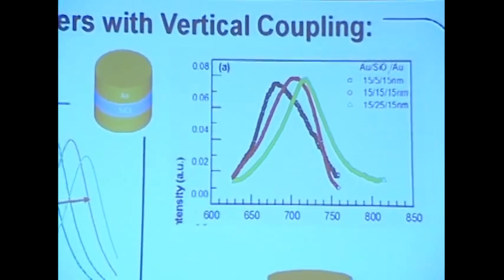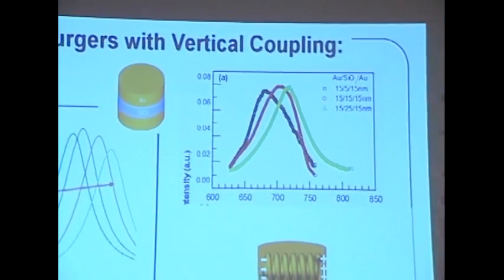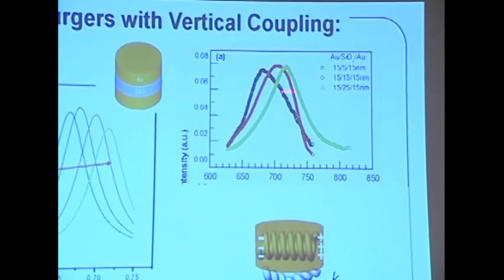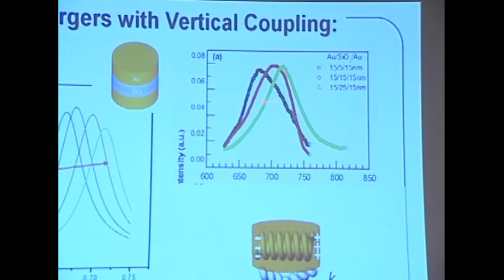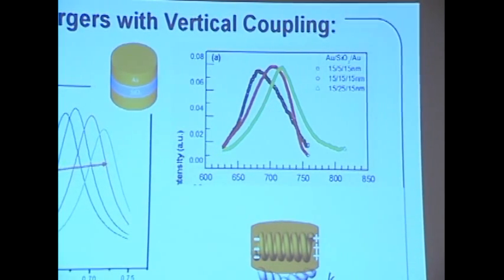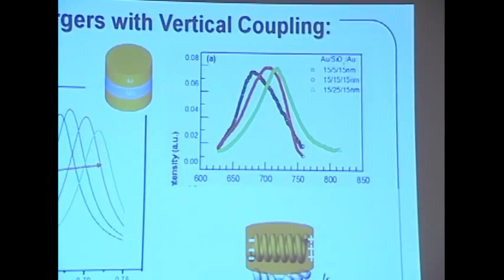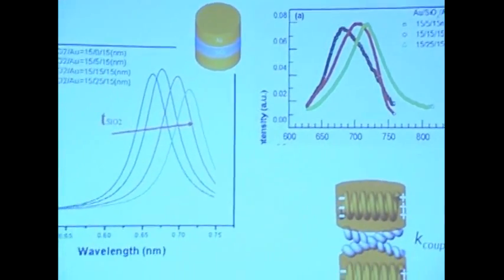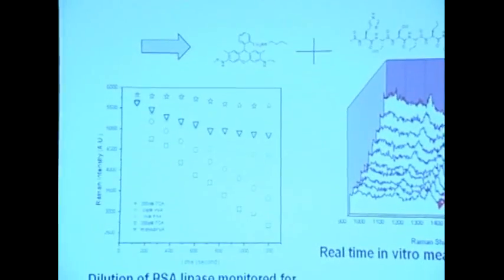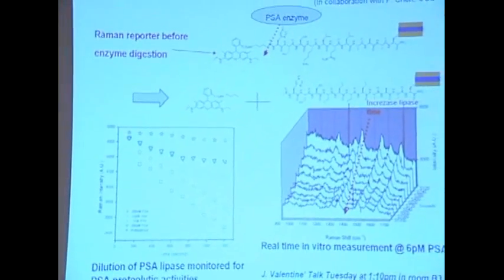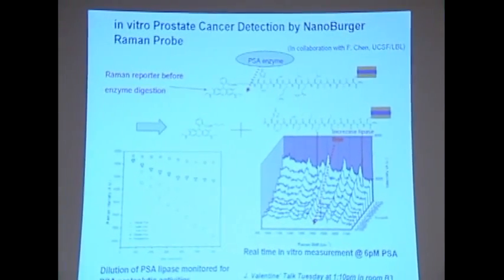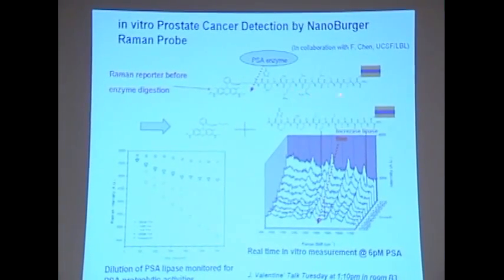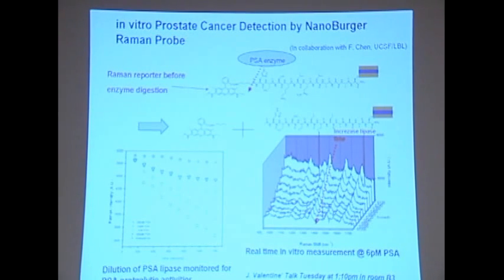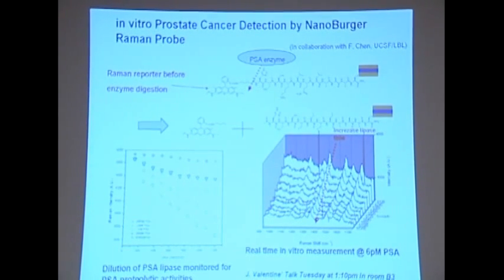It is a tunable spring, essentially, between the two resonators. And by using a different thickness, you essentially achieve resonance at a different frequency. This is especially useful for surface enhanced Raman sensing. So as one application, we collaborate with Frank Chen at LBL and UCSF. We use that for early diagnostics of prostate cancers.